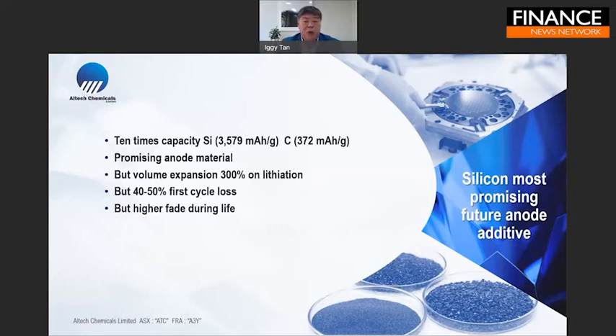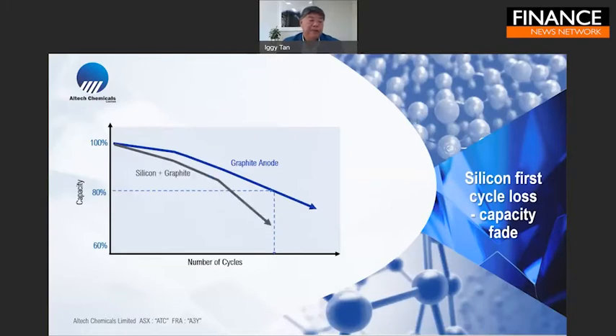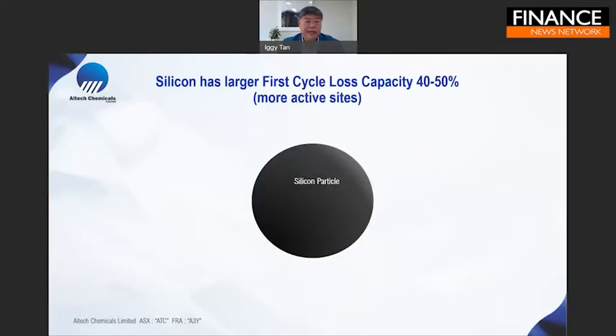Why isn't it being used in the anode material today? There are three major problems with silicon. The first one is that the expansion is 300% in volume. Number two, the first cycle loss instead of 10% is close to 40 or 50%. And there's also a high fade. So if you look at the graphite versus silicon graphite, you can see the fade drops off very quickly. And you actually have a reduced battery life if you try to use silicon today.